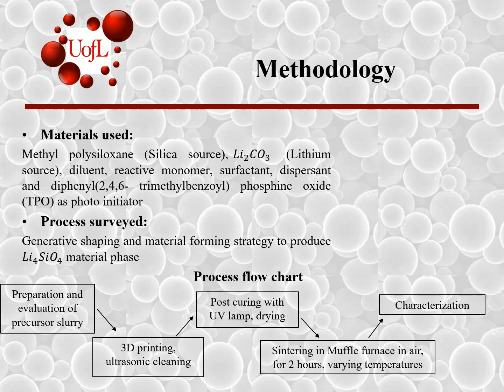The materials used for this process are methyl polysiloxane, which is the silica source, and lithium carbonate, which is the lithium source. Along with them, a diluent, reactive monomer, surfactant, dispersant, and a photoinitiator are used. We make a homogeneous slurry out of these materials, and the performance of the slurry is evaluated, followed by Vat photopolymerization to produce parts that undergo ultrasonic cleaning. Then they are post cured with a UV lamp and dried at 50 degrees Celsius.